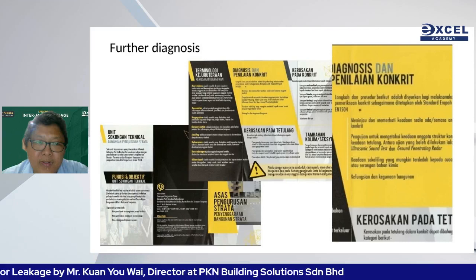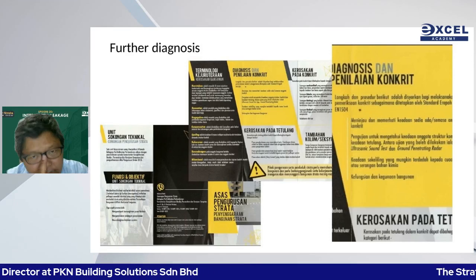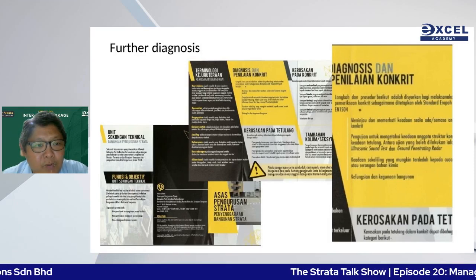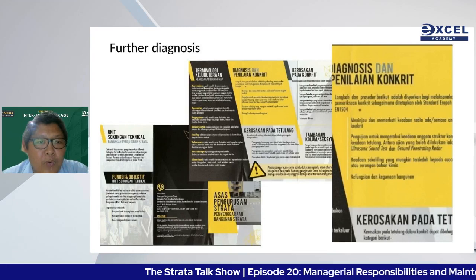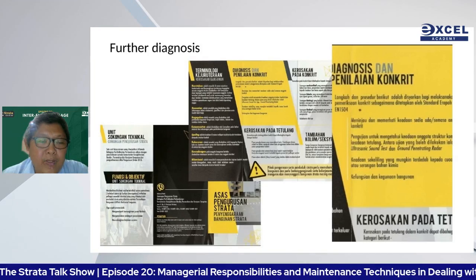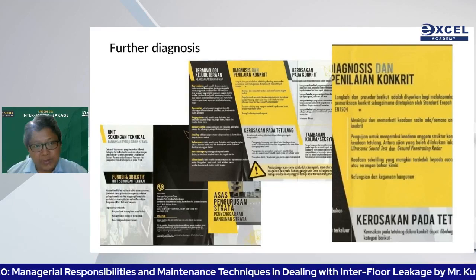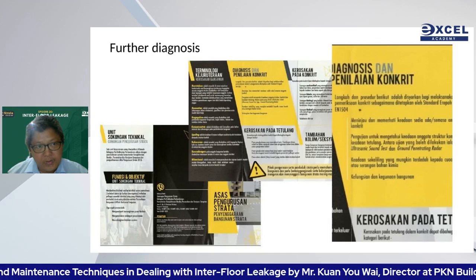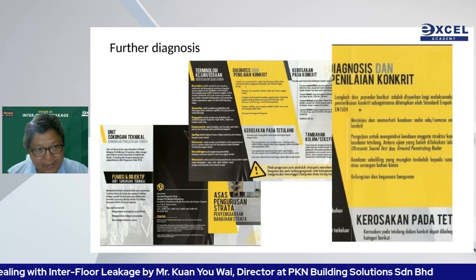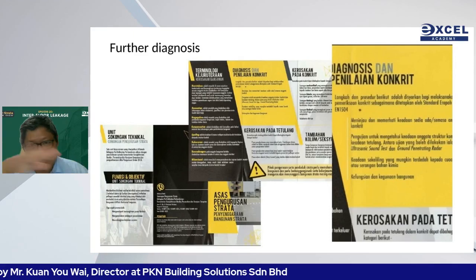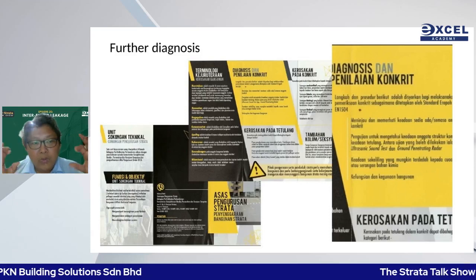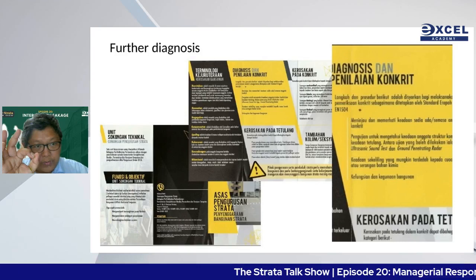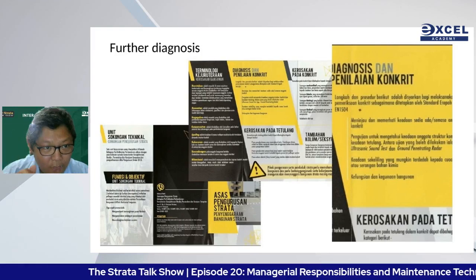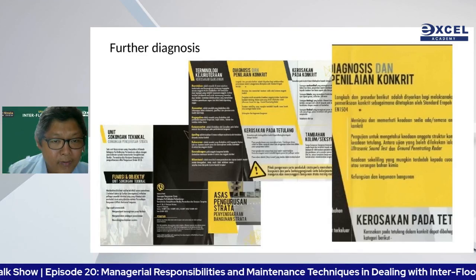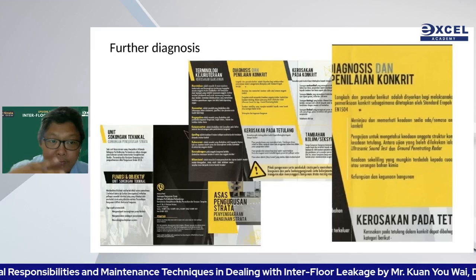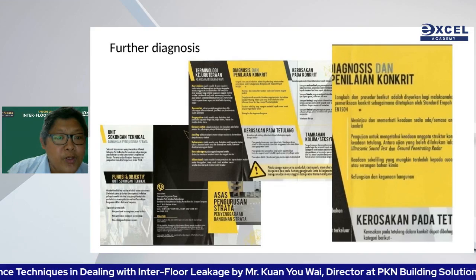Okay, JKR recommends that in the event of diagnosis and repair of concrete, do comply with EN 1504. EN 1504 is not only about waterproofing, but also corrosion control. So imagine if water starts to go into the concrete, the corrosion matrix has been formed, the anode and cathode sides have been formed, the corrosion has started, even though you waterproof on top of the surface of the swimming pool. Once the corrosion has started, the reinforcement steel bar will keep on expanding. It will expand up to 6.5 times its original size, cracking the concrete from inside. And this corrosion will continue, even though it will reduce in speed after you waterproof. So whatever you waterproof will soon crack.